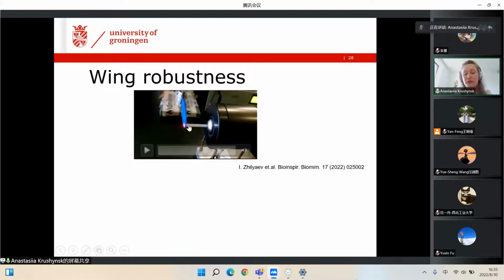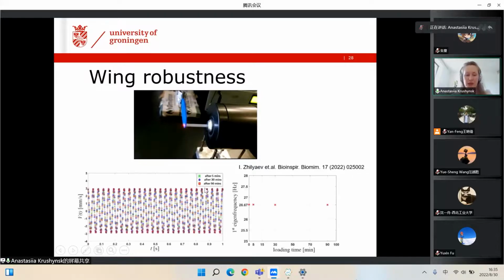So now instead of manual excitation, we used a shaker, excited the wing for different periods of time and measured the forced excitation response. So it looked like that. We excited it for 5 minutes, then the next round for 30 minutes, and then the same wing for the next time for 90 minutes. And then after each of these forced excitation experiments, we performed a free excitation experiment to check the eigenfrequency.